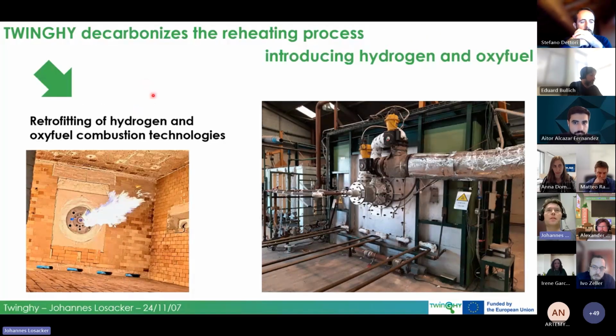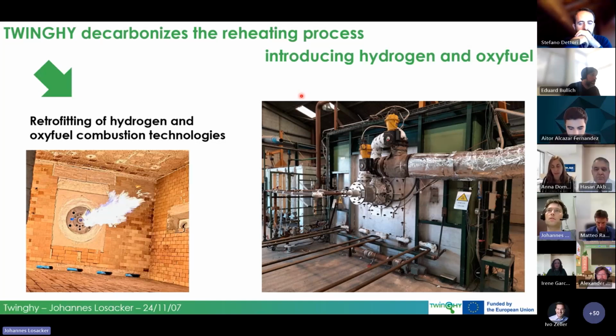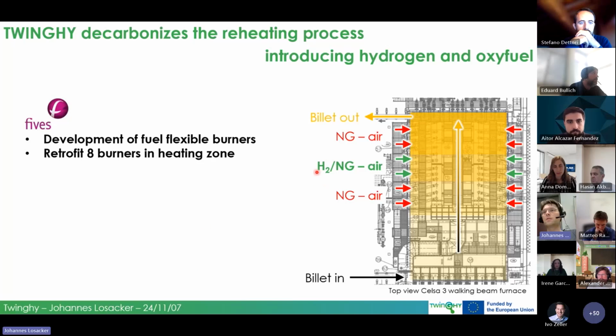So the scope of TWINGHY is to decarbonize, at least partially decarbonize, this reheating process. And we follow two major pathways to do that. The first and arguably most important one to reduce emissions is the introduction of hydrogen and also oxy-fuel. So we are retrofitting the furnace in parts at least by newly developed burners that are capable of firing hydrogen. And as most of you might know, firing hydrogen doesn't produce any CO2. And so that's our way to go.